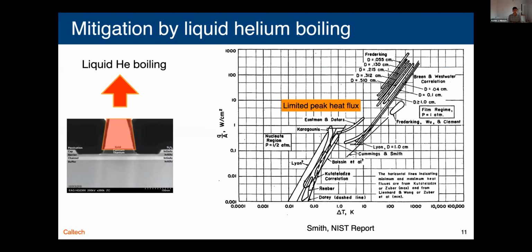There's some interesting heat transfer problems that occur when you try to experimentally do this. One of them is that liquid helium boiling has been extensively investigated in the 70s and 80s and even before that. And it's known that there's a limited peak heat flux for the superheat of any surface. And this limited heat flux is actually many times smaller than what's required to remove the heat flux emanating from the gate.